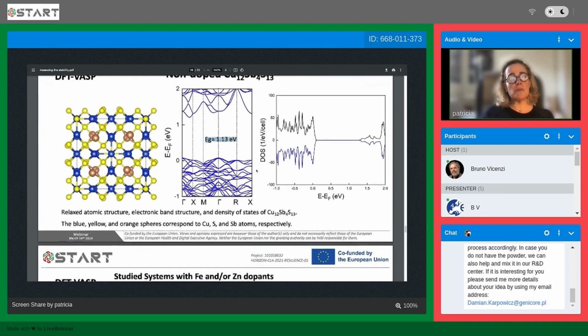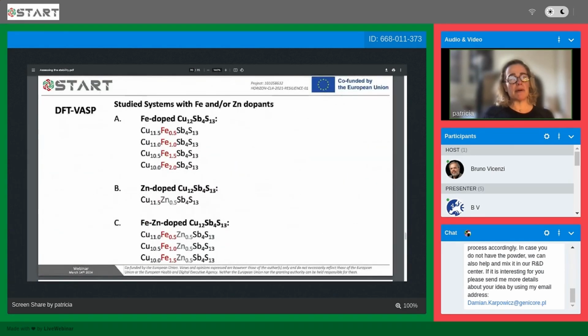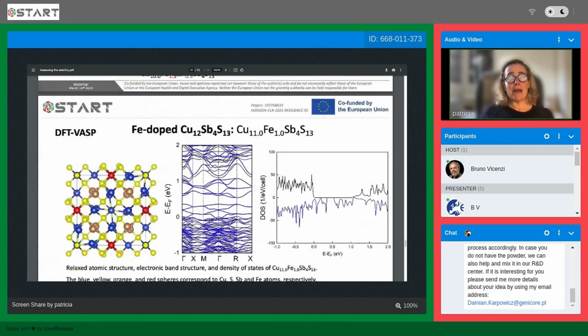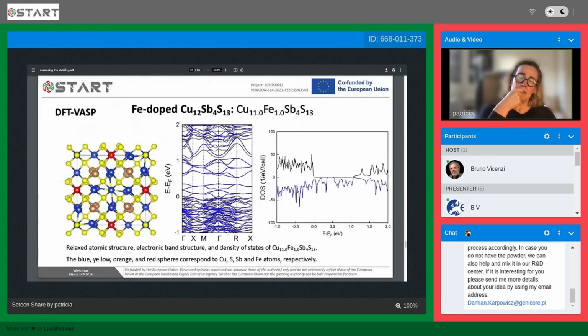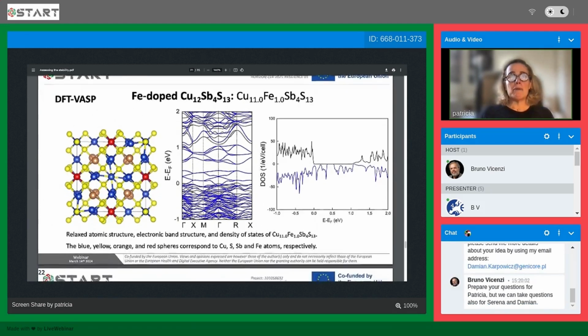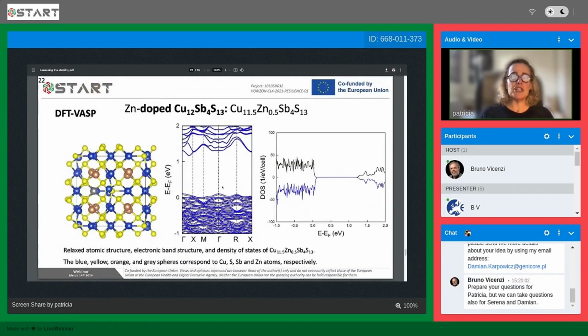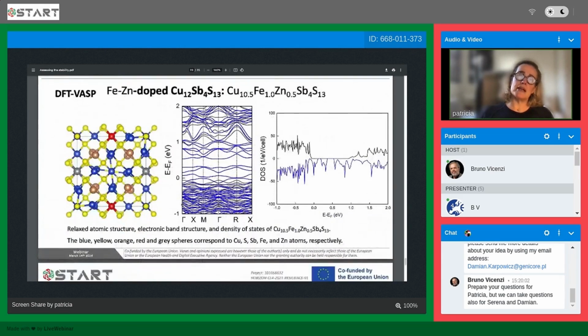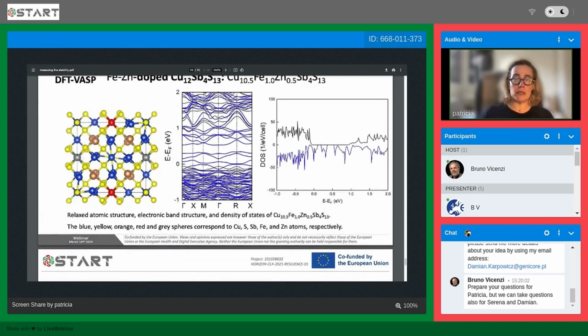So I'm going to show you now when we dope with iron, because this is what we have done, doping with iron and doping with zinc. What we see is that iron indeed has the influence of closing the gap, and this is usually what is best for tetrahedrite, to have a semiconducting material, but with a very small band gap. And this is what happens with the presence of iron, and that's why iron is one of the chosen elements by the START project. When we put zinc, then it's completely the opposite. So zinc doesn't really change the band gap that much compared to copper. And then, of course, when you mix both, when you have iron and zinc, then again you have the populated region here, saying that we have decreased band gap, which is interesting for the properties of the material in terms of thermoelectric behavior.